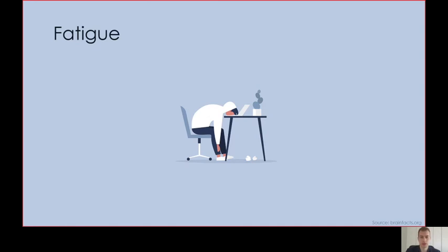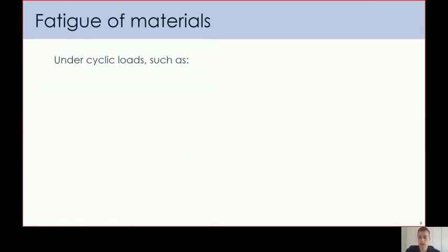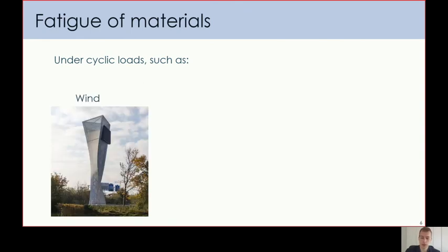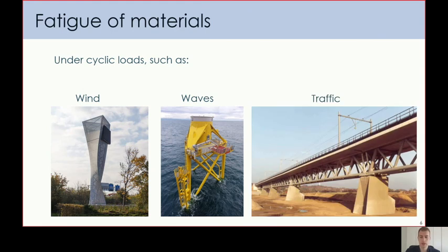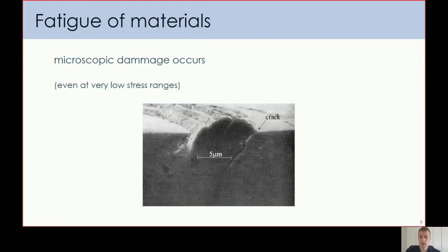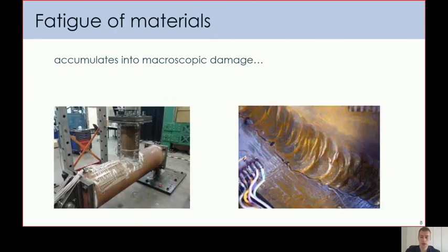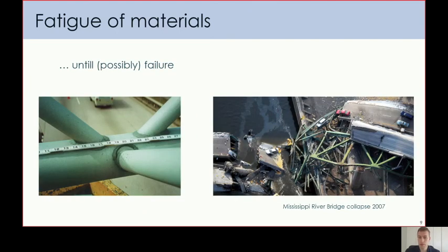Fatigue means that you're exhausted or tired. But for fatigue of materials, it means that under cyclic loads, such as wind or waves or traffic, there is microscopic damage happening in the material. And this can happen at even very low stress ranges. And this microscopic damage can accumulate into macroscopic damage, such as cracks that you see here, until possibly failure of your structure.